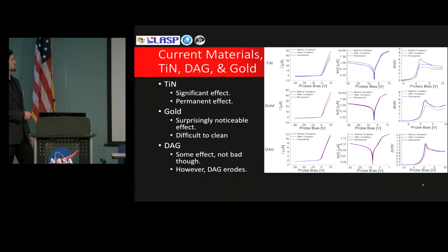Then we tested the current coating materials to see how those would react when introduced to plasma, or oxygen plasma. The titanium nitride not only had a significant effect due to the oxygen plasma, but also would not return to the control sweep, no matter how hard of a current I tried to clean this with. This suggests that once the titanium nitride gets oxidized and becomes titanium oxide, it is either in a lower energy state and it's stuck that way. It's not a layer that you're going to be able to off-gas or burn off. This is an actual chemical change in the composition of the layer.